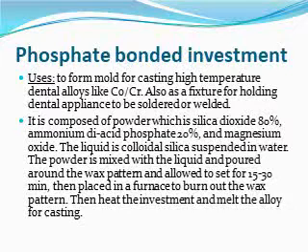Liquid is the colloidal silica suspended in the water, and the powder is mixed with the liquid and it is put around the wax pattern and allowed to set for 15 to 30 minutes. Then it is placed to burn out the wax pattern. Then the heated investment and melted the alloy for the casting.